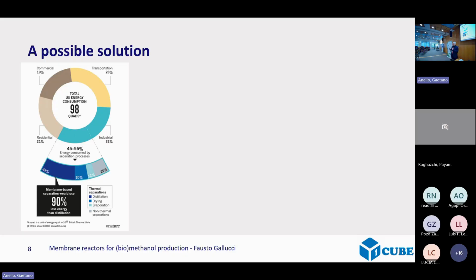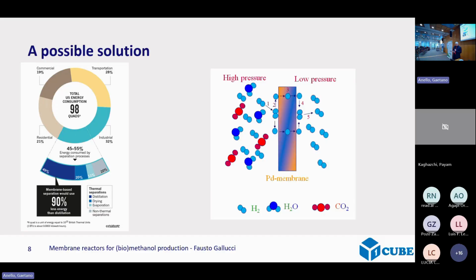And if you take these separations that are generally heat induced or pressure induced, and you change this with membranes, in many cases you can increase the efficiency up to 90%. Not for all, of course. Which means if you increase the efficiency, you decrease the energy that you use, so you decrease the CO2 emissions. That is the trick we want to achieve. And a membrane then is a separation layer that should be selective. And unfortunately, I put a picture of a palladium membrane, which is super selective to hydrogen, but it's not the topic of this talk.